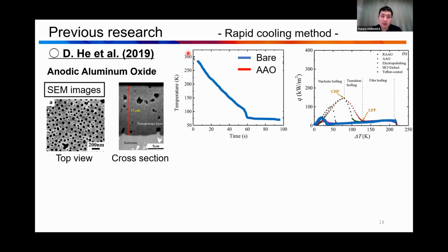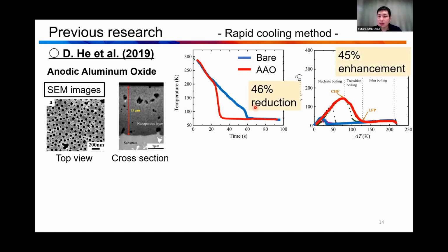So this is the bare surface case, and a cooling curve. It's like this. And this is the boiling curve. It's like this. But when we added this AAO surface, we can reduce the cooling time by 46%. And the boiling curve is here. This point is moved to the higher temperature point, and this enhancement rate is 45%.